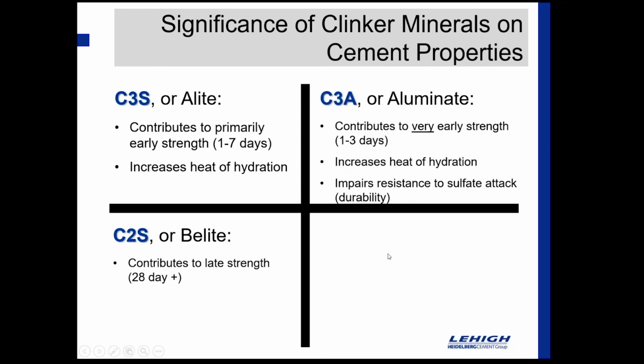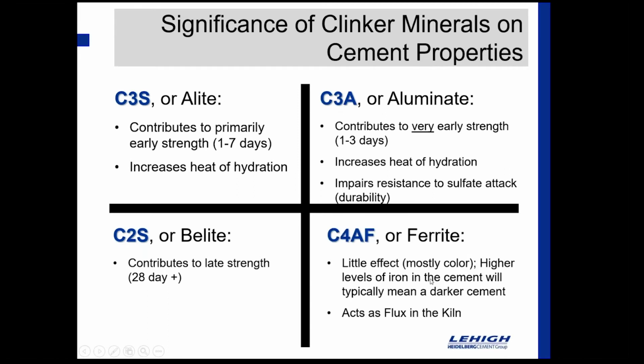C3A, or aluminate, contributes to very early strength gain. And again, now we're looking at 1 to 3 days. This is a source of the initial heat of hydration. And if this gets too high, you can impair your resistance to sulfate attack and lower the durability of the concrete that would be produced if C3A is not controlled.